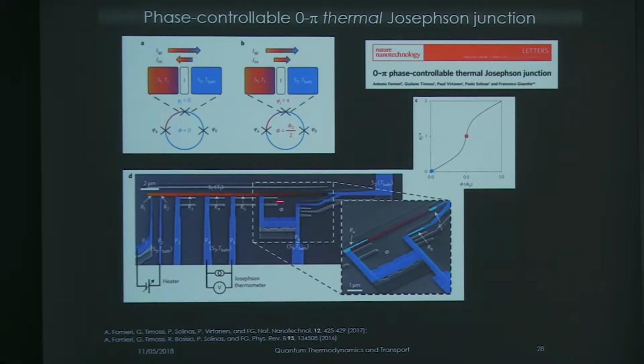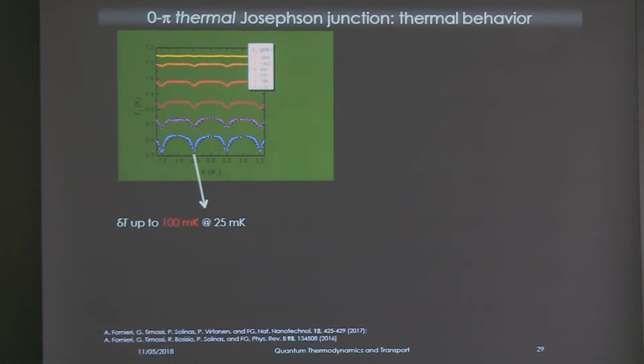This is more complicated. There is a fully superconducting structure in this case. Okay, and we have implemented the junction, where we obtain the full rotation, with a much larger resistance than the other two, so that all the phase drop occurs here, and we are able to completely phase tune the interferometer from 0 to pi. And what is nice is that in this kind of interferometer, we obtain the record temperature oscillation up to 100 millikelvin, because, of course, you can add also the other components.